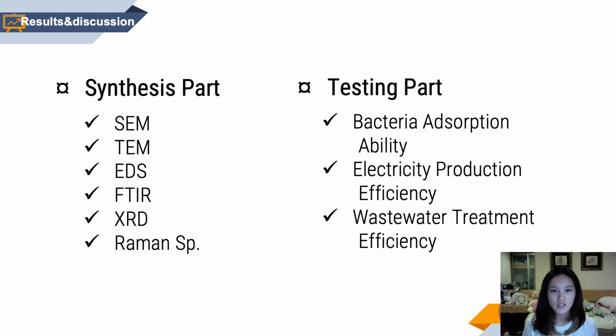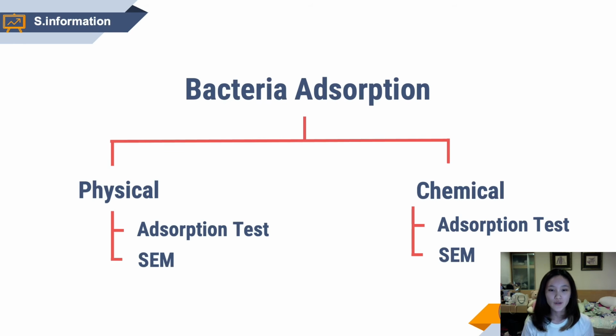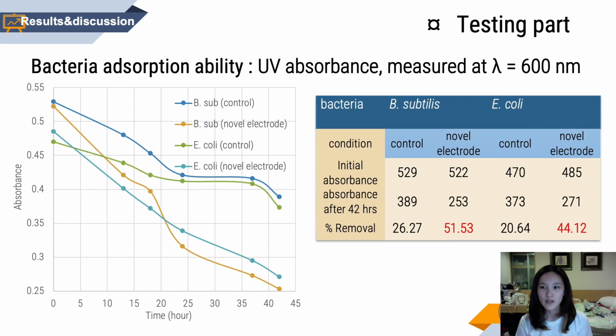Next is the testing part. We use SEM and adsorption tests to test both physical and chemical bacterial adsorption. First, for the bacterial adsorption ability, we put our electrode with our sample into each bacterial solution. By using the UV spectrophotometer at 600 nanometers, the concentration of bacteria when using our electrode has decreased significantly more than the control one for both E. coli and Bacillus subtilis.